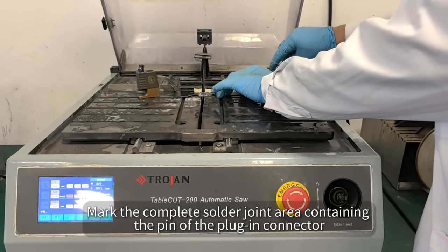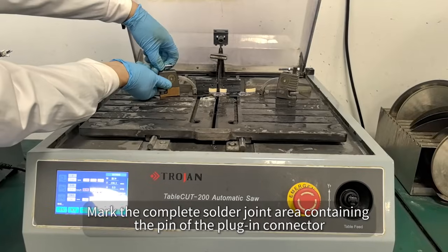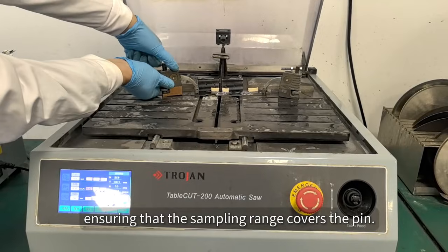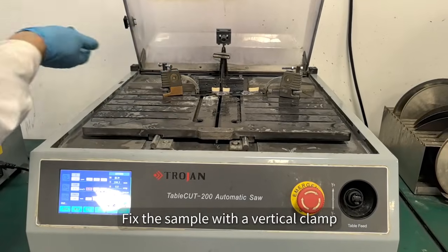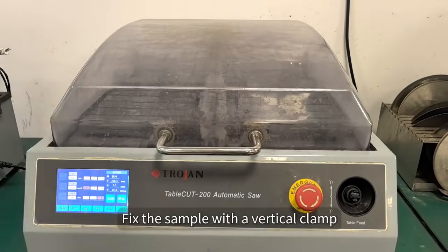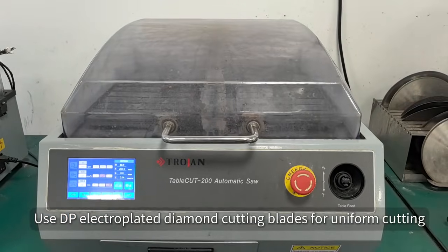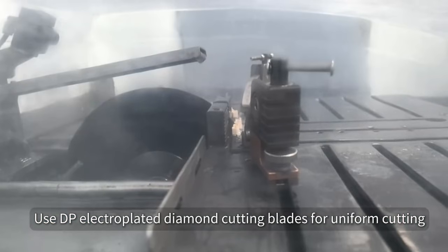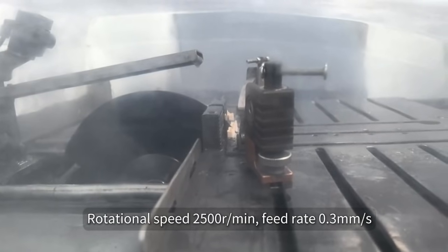Mark the complete solder joint area containing the pin of the plug-in connector, ensuring that the sampling range covers the pin. Fix the sample with a vertical clamp. Use DP electroplated diamond cutting blades for uniform cutting. Rotational speed 2500 R per minute. Feed rate 0.3 mm/s.